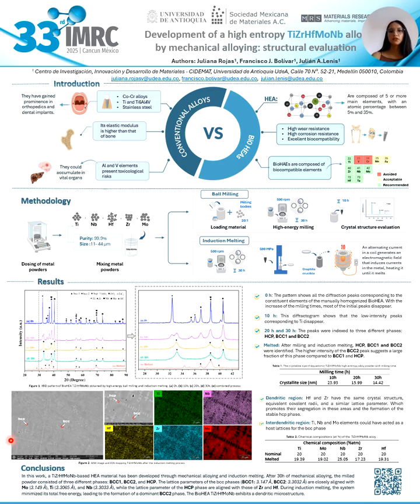The microstructure of the high entropy alloy after the induction melting process shows dendritic and interdendritic regions. According to the EDS analysis, the dendritic regions consist mainly of hafnium and zirconium. This is because they have the same crystal structure, equivalent covalent radii, and a similar lattice parameter, which promotes their segregation in these zones and the formation of the stable HCP phase.